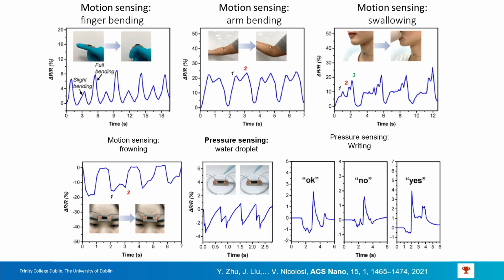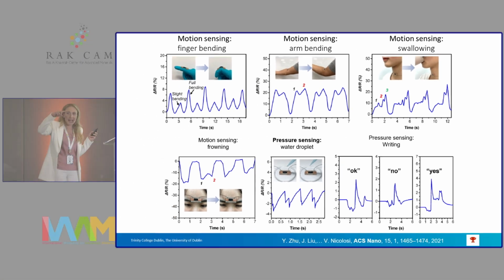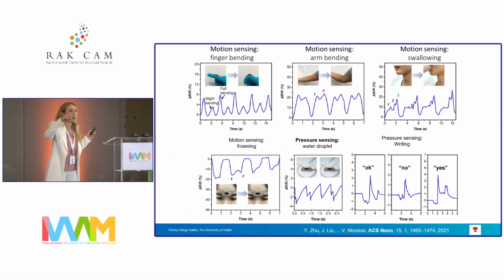One thing that we've also used them for is motion sensing. So this is, for example, one of these hydrogels stuck on the finger of my postdoc, and you can actually detect the bending of the hydrogel, in this case, because you corrupt the percolation of your sheets in the polymer. So you change the electrical conductivity.